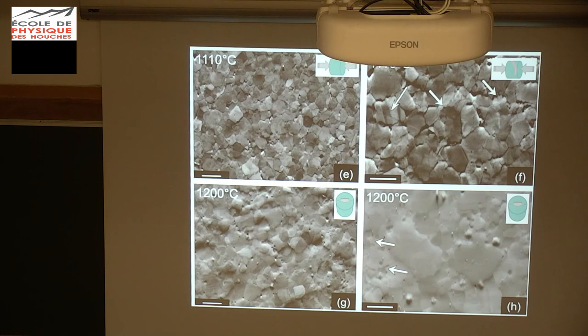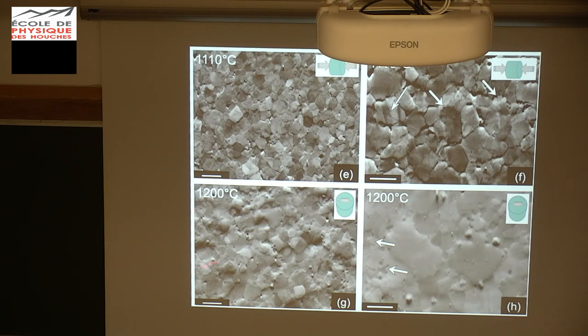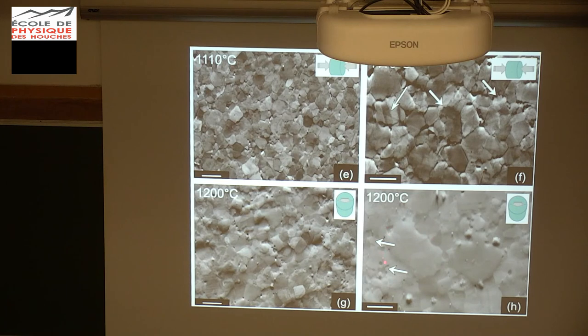At 1200 degrees Celsius, it's completely different — typical dislocation creep features of olivine, so high temperature features. You can even see some grain boundary activities. And no gaps, no voids, no asperities along the grain boundaries. Because I'm very picky, and I'm lucky to have good colleagues in France who are really good in TEM, I asked Patrick Cordier to have a look at these weird samples.